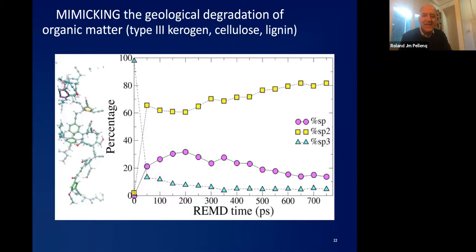All right, so let's analyze the texture of the carbon phase. As I told you, what we're doing is producing a lot of tiny molecules, but also the carbon is gathering the atoms together and forming a bigger structure, which is on the right, for instance. And you can see, for instance, rings of six carbon. These are aromatic rings. Typically, at the end of time, some of those molecules can become graphite or graphene, actually. All right, we can do it synthetically these days, of course, but this is the same carbon chemistry. What's interesting, as I said at the very beginning, is that this reactive approach is a way to decide what kind of bonding I'm getting in the system.